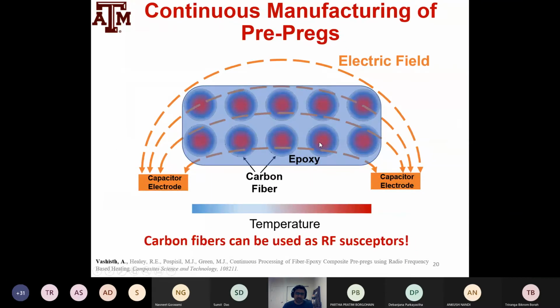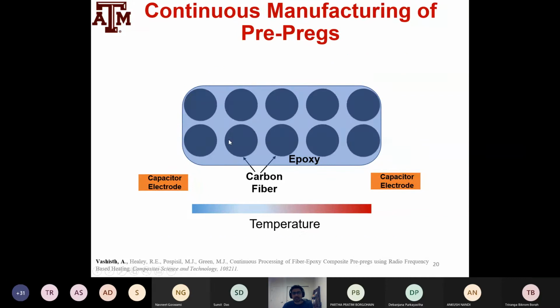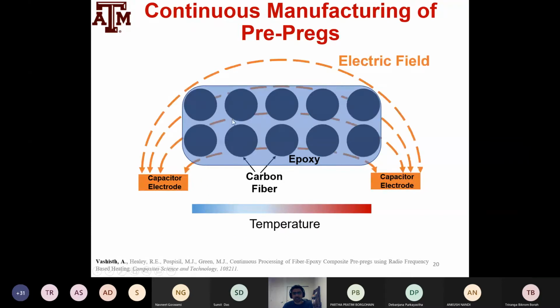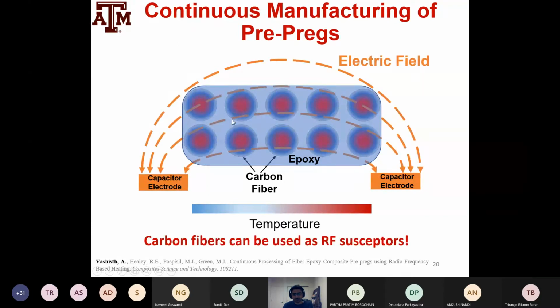So this is how it would work, or we figured out it would work. If you have these composites, you pass RF fields through the composites, and the carbon fibers start heating, and you have more or less a volumetric heating type of mechanism where the whole volume or the cross section of your composite heats up rapidly.